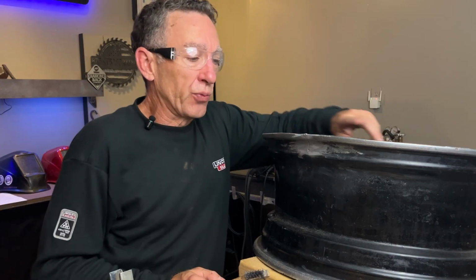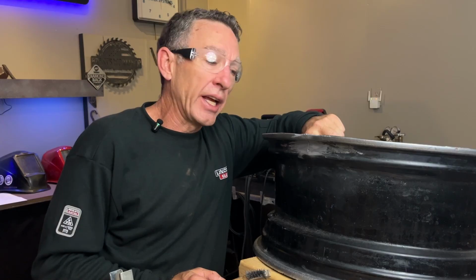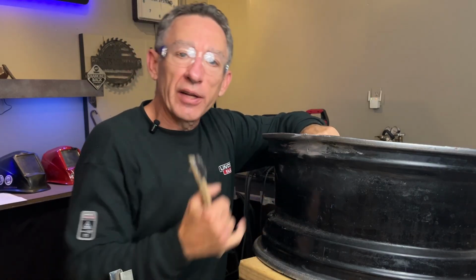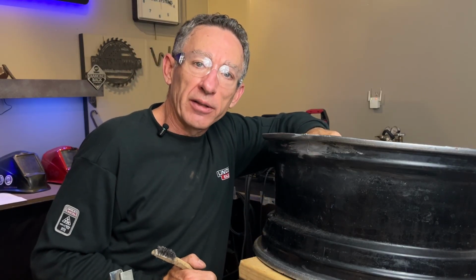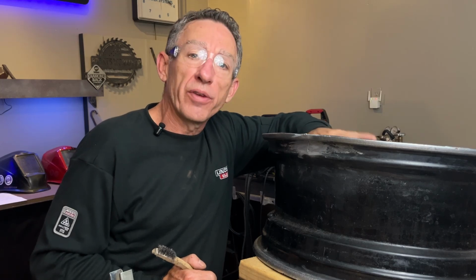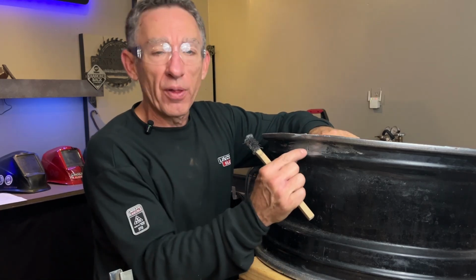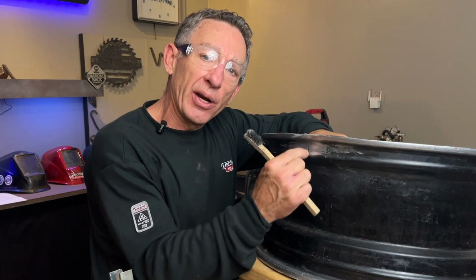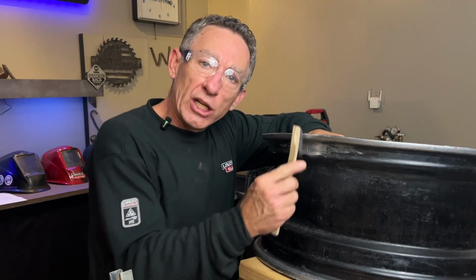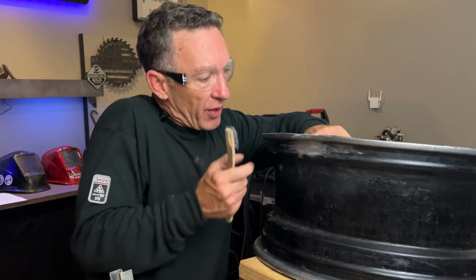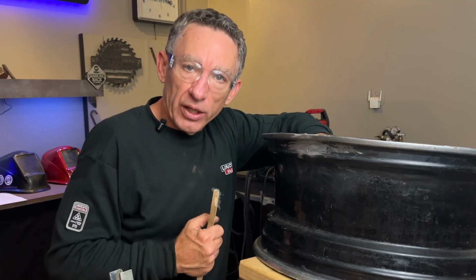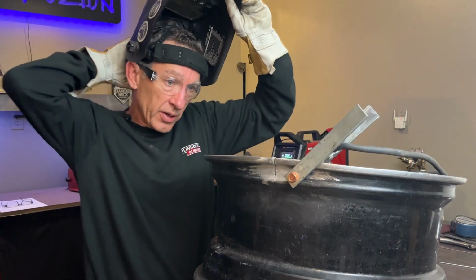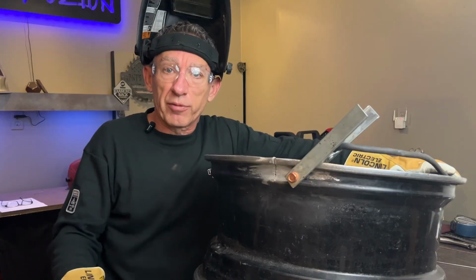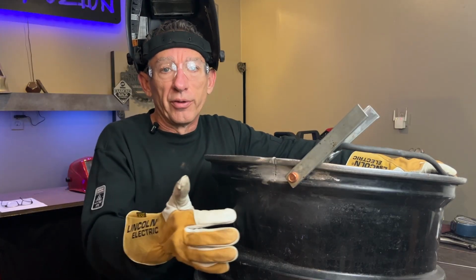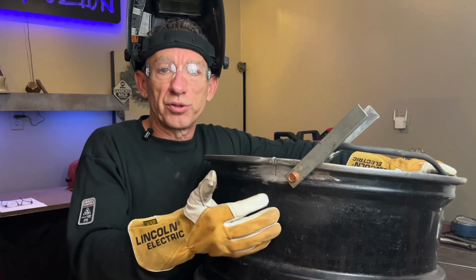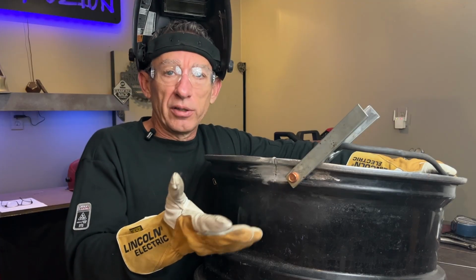On a weld like this, where we didn't shield the backside from oxidation, you can bet that down inside that groove, we've got a heavy, thick oxide layer on the backside of that weld. So what we've got to do at a minimum is open this up a little bit so that we can get down in there, get it into bright metal. We'll re-clean it with our stainless toothbrush, and then we'll go ahead and put our back pass on here and seal this thing up. All right. Always best to weld in the flat position and have gravity work for you. I'm going to weld this in the vertical up position right now because we're tipped slightly uphill. And it's going to do a couple of things.